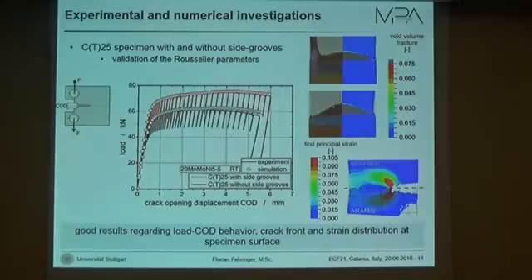So after the numerical calibration, we did some validation of our Rousselier parameters. We used 2 different CT25 specimens, with and without side grooves. And as you can see in the middle, with the parameters we obtained from the notched round bars, we were quite capable to describe the load crack opening displacement behavior for both the side-grooved and the non-side-grooved specimen.